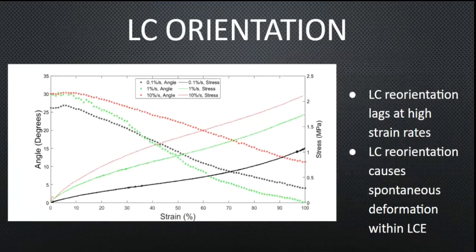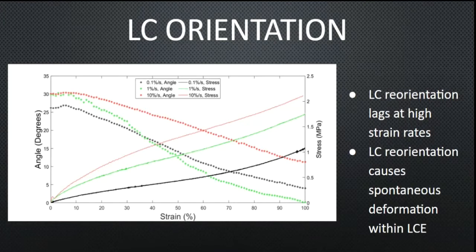In addition, we did experiments with liquid crystal reorientation. Here is a graph where you have the angles as dots at each strain as you stretch from 0 to 100% strain. The 1% per second and 0.1% per second curves agree pretty well, while the 10% per second curve is higher than both — showing that at 10% per second the liquid crystal orientation lags behind that of slower strain rates. Also, as the liquid crystals are reorienting, the slope of the stress-strain curve is pretty small, meaning that liquid crystal reorientation is causing some sort of spontaneous deformation within the LCE, since the rod-shaped particles help the LCE deform in the direction of force as they stretch.